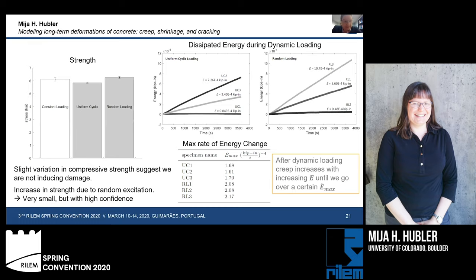If we take a look at our strength results, they initially look very uninteresting. There's only a slight variation in compressive strength, but the good thing is that this suggests that we did not induce damage. What we also see is that there's actually a slight increase in our strength due to the random loading. And I realize it's very slight, but notice a pretty high confidence because we have plotted our bounds here for a very large set of tests.